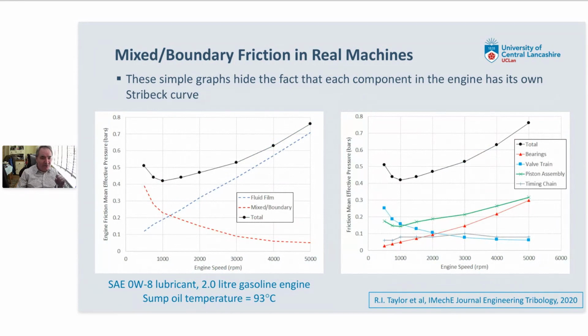Now, I should say that this simple graph on the left hides the fact that each component really has its own Stribeck curve. So this is the same data plotted again on the right-hand side, but in terms of the different component contributions. The blue line shows how the valve train friction varies with speed, and it just keeps on going down with speed. So over the whole speed range of this test, the valve train is in the mixed and boundary friction regime. We can contrast that with the red line, which is the journal bearings, and in that case the friction is simply going up with speed over the whole range, which suggests that the bearings are completely in the hydrodynamic fluid film regime for this test. Then you've got the piston assembly, the green line, which is predominantly in fluid film lubrication for speeds above about 1000 RPM, but at the lower speeds we're seeing some mixed and boundary friction there as well. And then the timing chain is a bit complicated, but it's a fairly small contributor to this engine friction.